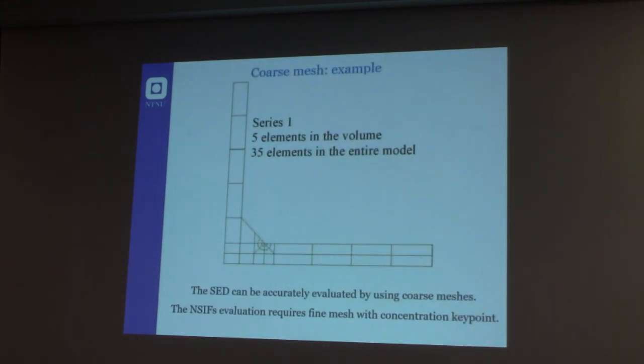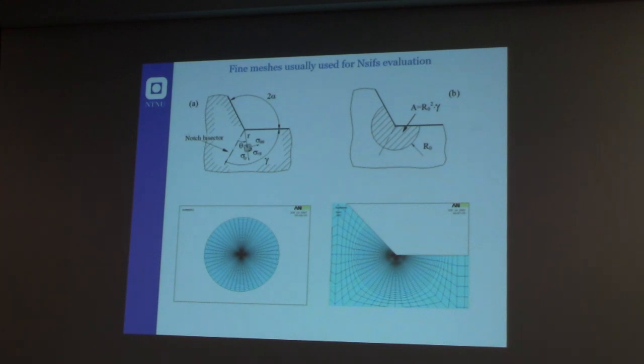So you don't need a very refined mesh for making any calculation. This is only a plane case, so a bidimensional case, but if you consider 35 elements in the entire model and 5 elements in the volume close to the notch tip, you can evaluate the strain energy density very accurately. If you want an accurate value of the notch stress intensity factor, you need a very fine mesh like this close to the notch tip, which is very, very heavy